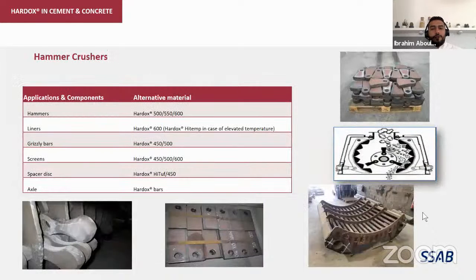In the hammer crushers, this is a very important part. Again, in some liners, if the temperature is still very high, we can use Hardox high temp. In other cases, the hammer itself can be produced from Hardox 500, 550, or 600. The main thing is that sometimes the hammers are quite thick, up to 120 millimeter. Sometimes Hardox availability in the local market cannot be there.